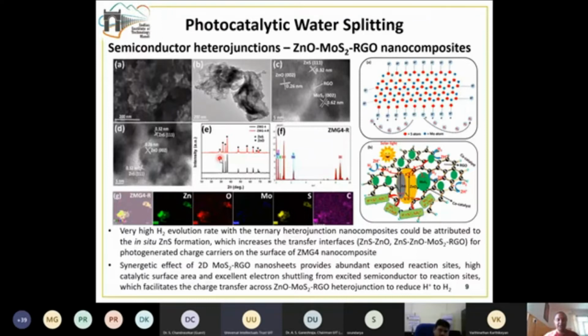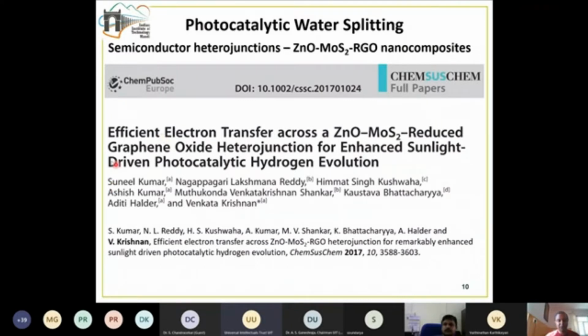And although this zinc sulfide is formed, it is playing a very positive role in this case, because the number of transfer interfaces gets increased because of the formation of the zinc sulfide. So now we can see zinc sulfide, zinc oxide, MoS2, and RGO. Actually, this ternary nanocomposite becomes a kind of quaternary nanocomposite during the process, and that leads to better separation of the photogenerated charge carriers, leading to better photocatalytic activity. So we could clearly see that there is a synergistic effect between MoS2 and RGO when it is coupled with zinc oxide, and this leads to better production of hydrogen gas. And this work was done by my former PhD student, now Dr. Sunil Kumar, and was published in the journal ChemSusChem in the year 2017.